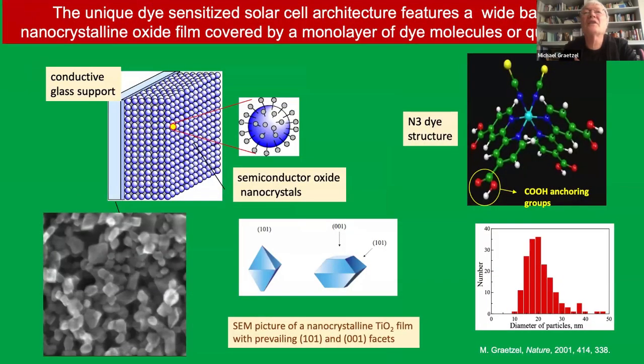And so finally, the structure which evolved at the end, or in the beginning of the 1991 paper that Shahzada mentioned, was an electrode consisting of an array of nanoparticles of semiconductor oxides, TiO2 in this case. And so, yeah, we could form those films very easily by screen printing, and the colloids were easy to make. And so you can see on the left a SEM picture of the colloidal film, and you can see the TiO2 nanoparticles annotated. And this is the 101 facet, this facet you can see here. And that's actually the prevalent facet on those particles. It's the lowest energy facet.